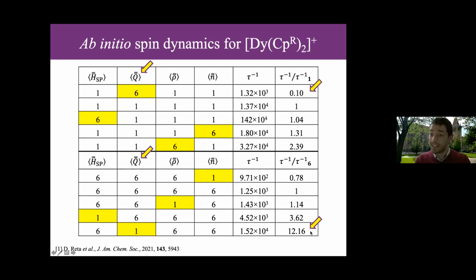And so these are not exactly the same numbers, because remember, these rates correspond to the second, so the smallest non-zero eigenvalue of a 16 by 16 matrix. And it's not trivial when all of these things are taken as products together, what that comes out as. But you can clearly see here that they are the same order of magnitude change, which tells us the same thing, that this occupational term is the discriminant between the worst dysprosocenium single molecule magnet and the best dysprosocenium single molecule magnet. So it's simply the occupation of the vibrational states.